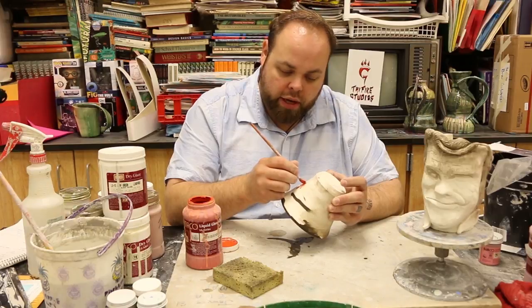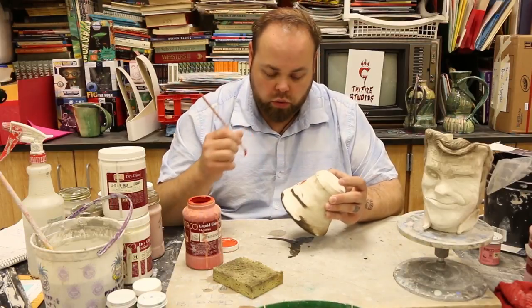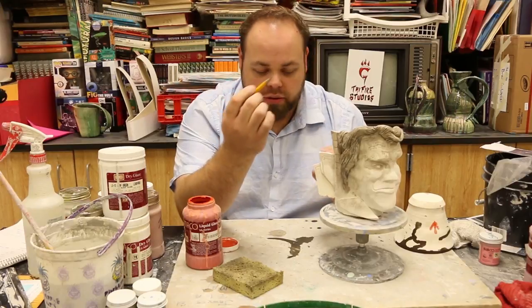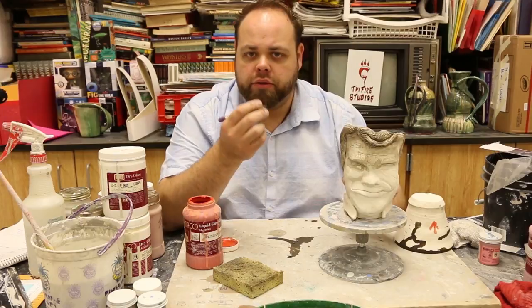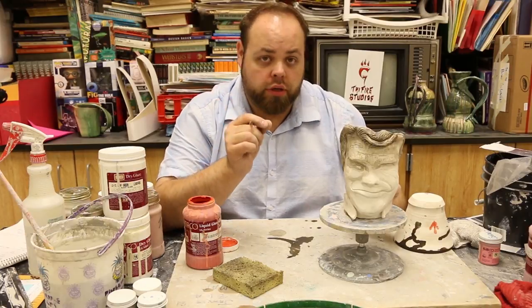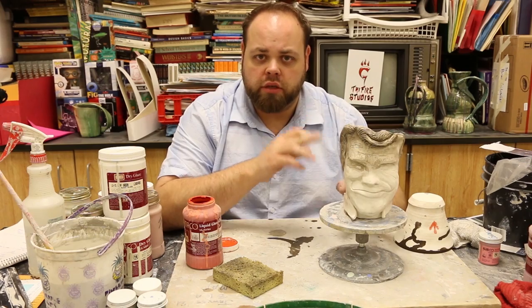If you need to paint a line the other way, draw it on the other way so that you can still pull the line down to create those patterns and designs. Take your time — it's going to take about two coats of the glaze so that you have that color on there nice and solid. Before you start glazing, take your piece and if you didn't design it out during the build phase, take a pencil and draw your design on there first. The pencil is going to burn off during the firing anyway — it burns off early in the firing stages and doesn't affect the glaze or the clay at all. Use it as a tracer guide so while you're painting your colors, everything comes out nice and neat.